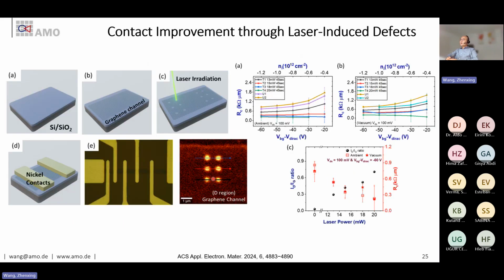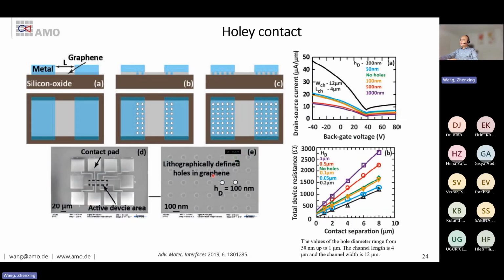And another thing is that for doing this kind of holey structure, you usually use e-beam lithography, and you can see the diameter is like 100 nanometers. So it's very challenging to do that. Also, it's very time consuming. Then we were thinking maybe there is a direct way, because you have to do lithography, spin coating and so on, then exposure, and then development and etching.